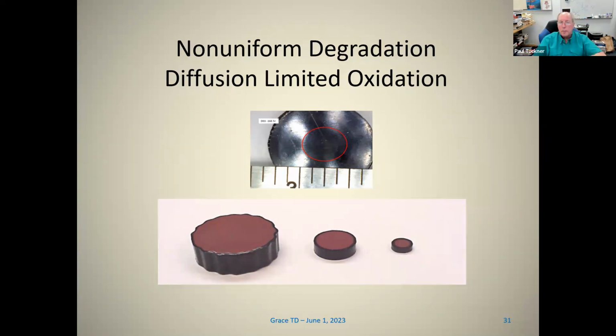But in this case, with some orange HNBR specimens, you could see that they degraded from the outside in by turning black, but it's a larger percentage of the small one than it is of the large one. So you'd find that the percent retained sealing force was best for the larger specimen and worse for the smallest one.